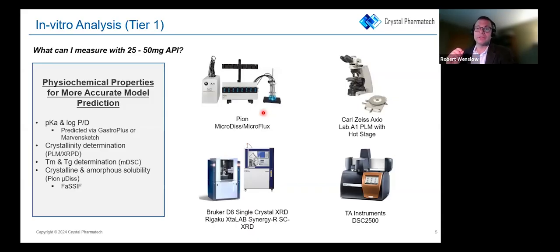But we're actually going to get an amorphous solubility with the small amounts of amorphous material using Pion systems. The Pion microDISS system will allow us to do amorphous solubility determination with, say, 5 to 6 milligrams of material. And it's a live kinetic measurement of the amorphous solubility and the precipitation rate of the amorphous. It's difficult to pull the sample out for an X-ray, but you do measure concentrations very well using that system.